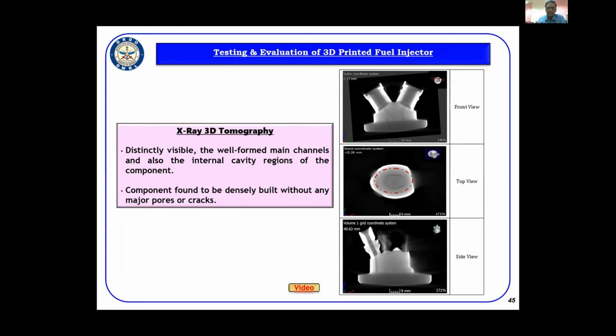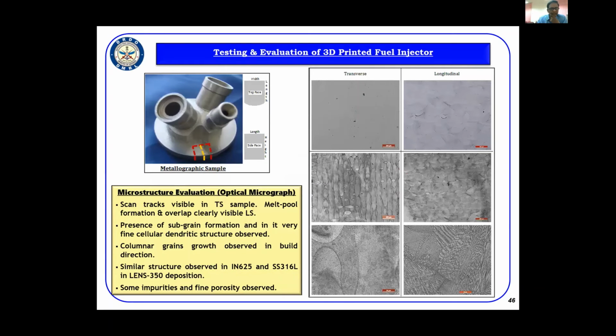We can't go with destructive testing of this component, so we have opted for X-ray 3D tomography, where the images have been taken at different layers, and we have seen very distinctly the well-formed main channels and also internal cavity regions, and the component also has been found to be densely built without any major pores. These are the pictures we have taken from the computer tomography. And then we have taken a small piece.